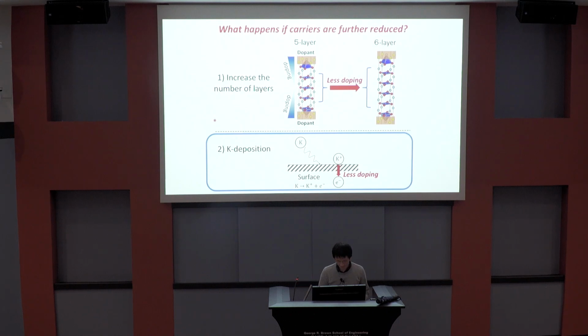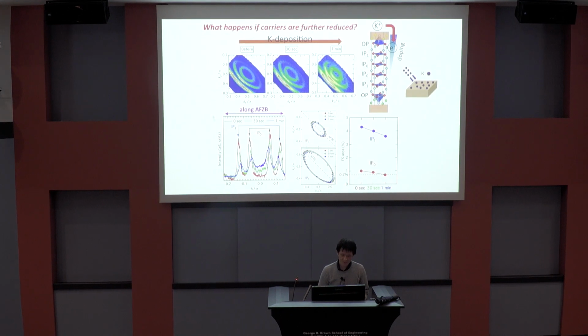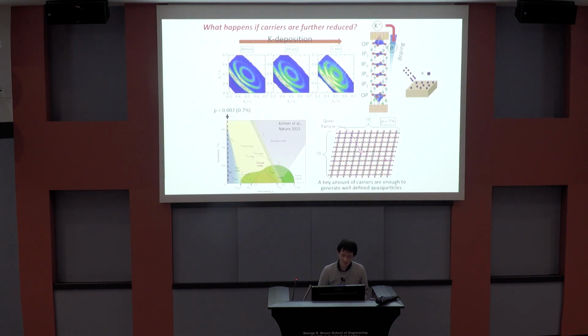Sorry, one more minute. So what happens if you potassium dope? This is the result without potassium deposition and after potassium deposition, and the pocket size becomes smaller and smaller, and we could even reduce it down to 0.7%. Still, the quasiparticle survives. That means a tiny amount of carriers is enough to generate well-defined quasiparticles in the clean system of the Mott layer.